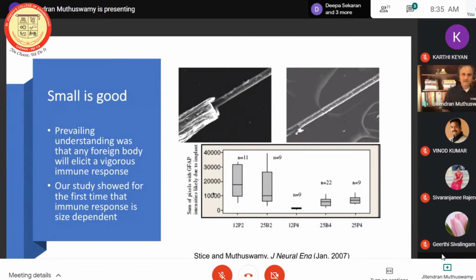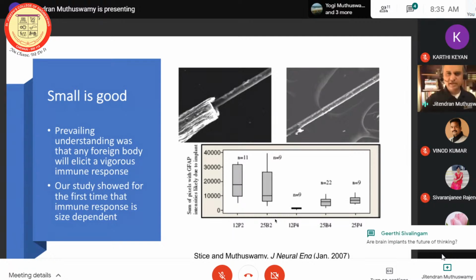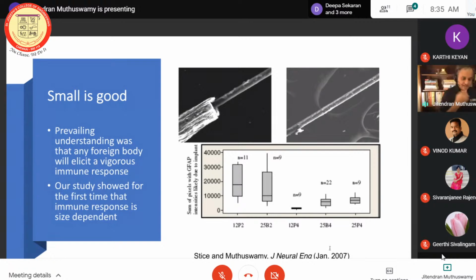Turns out we got a surprising result. What I'm showing you here is the tissue response on the y-axis, and on the x-axis is the size of the electrode. So this is a 12 micron electrode after 2 days, a 25 micron electrode after 2 days, not much difference. But if you leave those electrodes for 4 weeks, the 12 micron electrode has significantly less tissue response than the 25 micron electrode. So it is size dependent, which is interesting. The tissue response mounted by the body actually pays attention to the size. There are certain sizes that it actually ignores, or does not really care much about.